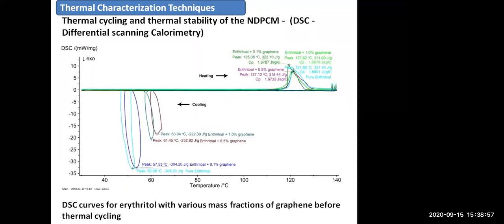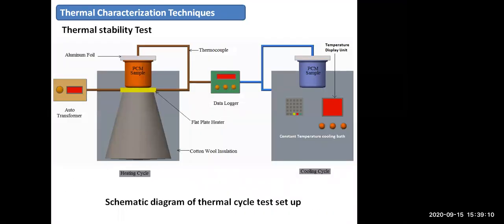Then the differential scanning calorimetry was used to determine the latent heat and the phase change temperature of melting and freezing of PCM and NDPCM. Thermal characterization techniques. The thermal cycling test is used to know the long-term stability of the storage material. The thermal cycling system was designed to operate between 30 degrees Celsius and 140 degrees Celsius. In total 1000 cycles, each cycle consisting of one melting and one freezing process, were done.